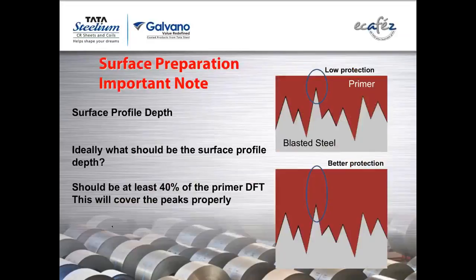Another thing is, what should be the surface profile depth? Because there's a big confusion in industries. Usually we recommend 40% of primer DFT should be your surface profile. For example, on the right side you see both photographs. On blasted steel you can have very low protection from the primer. Suppose my surface depth is 40-45 microns and I am putting only 50 microns of primer. On peaks I will have 5 or 10 microns or 8 microns of thickness, which is going to have low protection and ultimately convert to spot rusting.